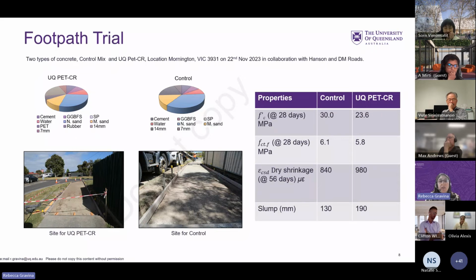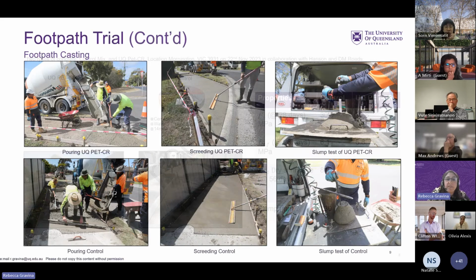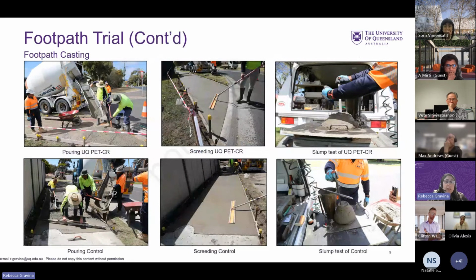It was a really good experience in terms of being able to work with the contractors and for them to get a feel of the material and what it looked like, and the responses were quite positive in terms of how they were able to deal with the material, because there was quite a bit of slag in this mix. It did look different, did feel different, so it's not the concrete type of mix that most footpaths are constructed with, but the contractors were able to cast and finish it.